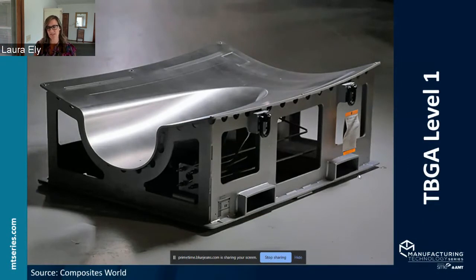One of the problems they had is they needed a tool material that closely matches the very low coefficient of thermal expansion of typical carbon fiber reinforced polymer. So when they went to cure the CFRP prepreg, they needed the tool not to be moving significantly. You can't use something like aluminum, which is going to move all over the place. The old solution, during prototype and low volume production, was that tools were fabricated via hand layup and autoclave in the same material. So they used CFRP tools to lay up the actual parts on. But those tools are not robust enough for a production environment, so basically they had to be scrapped, and then you'd have to make a new round of tools.